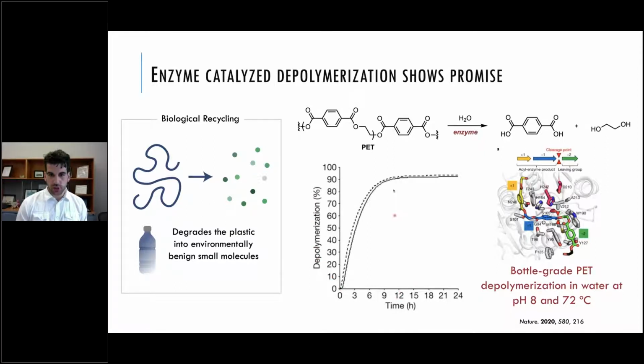So after about 12 hours, you depolymerize about 90% of that PET in that water. So right, this has been a field that's been going on for a long time. I think it's really interesting that they now have engineered an enzyme that's thermally stable enough to heat this up to 72 degrees Celsius. Obviously, when you want reactions to happen faster, you want to heat them up.